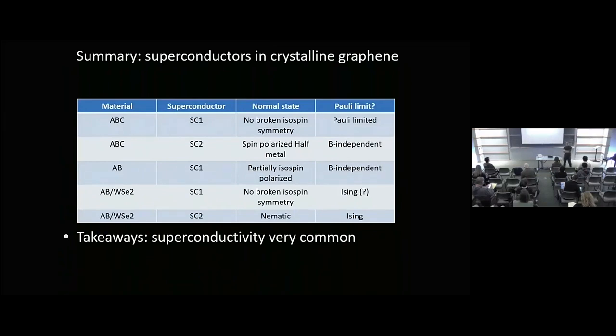I mean, we've just succeeded in making a sample that has such a geometry. Sadly, it doesn't have very many contacts on it, so we can't measure transport, but we can measure magnetometry and capacitance, and it's different. And I'm dying to know what transport will show. There's actually, credit to, I think it was Paco Guinea's group, they actually made a prediction before an experiment was done, which is that it's not going to help as much as in Bernal. And I'm curious to see if that turns out to be true.